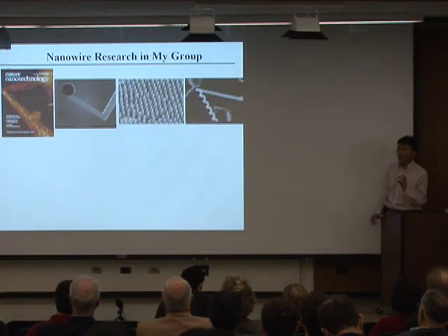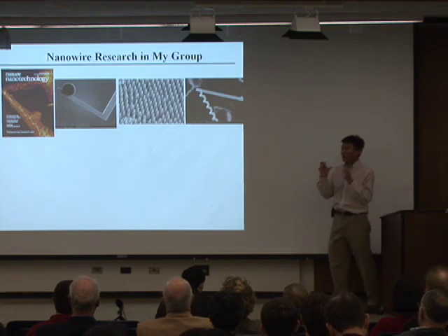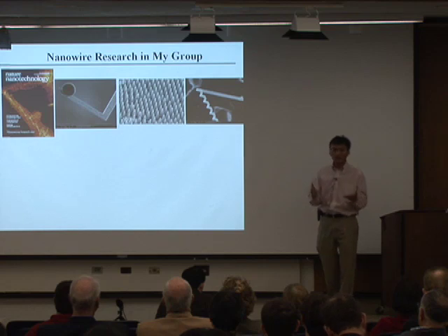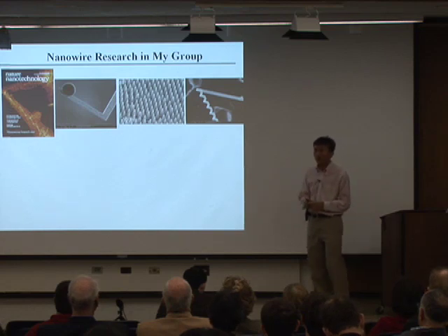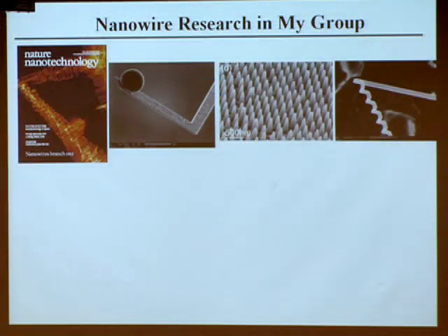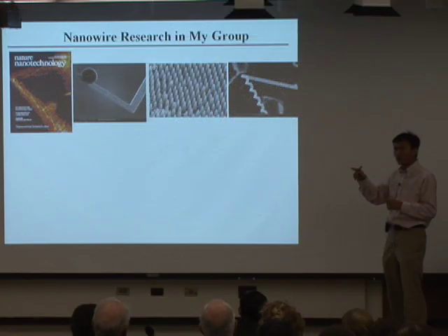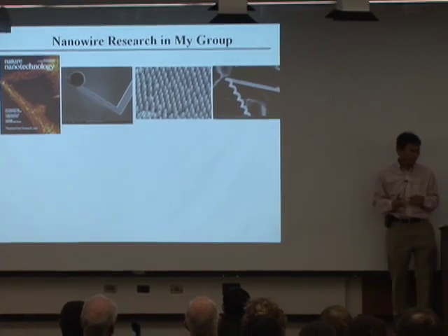In my own research group, the focus has been how do we really think about tailored nanomaterials for energy applications, also for other applications. So we figure out how to control the shape. In this case, this is a nanowire with the branch structure coming out, and these beautiful helical branches. By controlling the growth condition, you can form a really nice ribbon. You can make these vertical pillars. This is not only pillars, this is a cone-shaped structure. You can make this a helical structure as well. You can control it to certain degrees now.